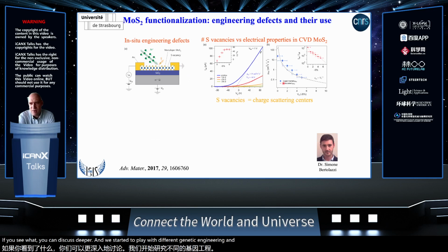And the idea was pretty simple: any kind of MoS2, for example from CVD, has a sulfur vacancy every 10 by 10 nanometers. And of course, the sulfur vacancy is a charge scattering center. So it's something that you don't really want to have if you want to do fast electronics.